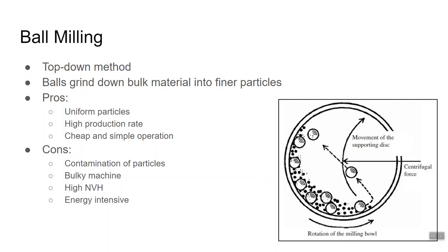The disadvantages are that the balls can contaminate the nanoparticles. Remember that the balls grind the bulk material, so there is wear between them. Other disadvantages include the size of the machine, the high levels of noise and vibration from the machine, and the energy required to operate the machine.